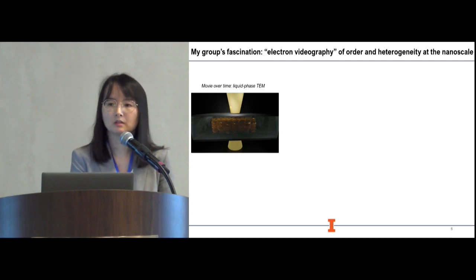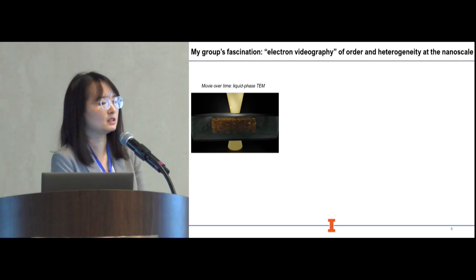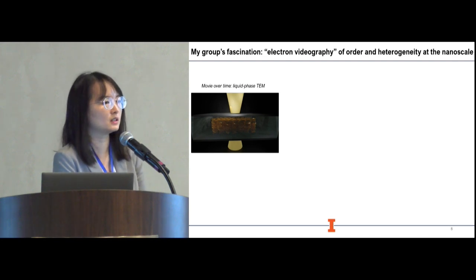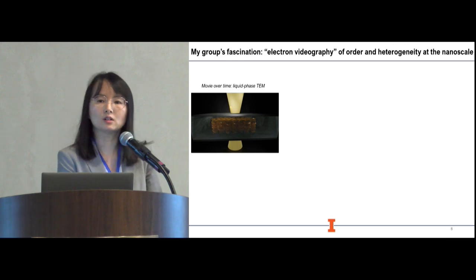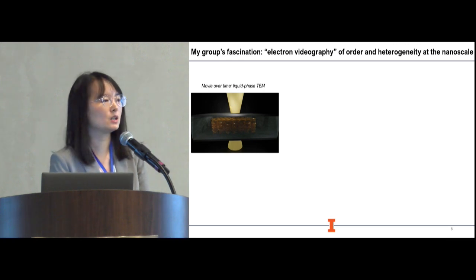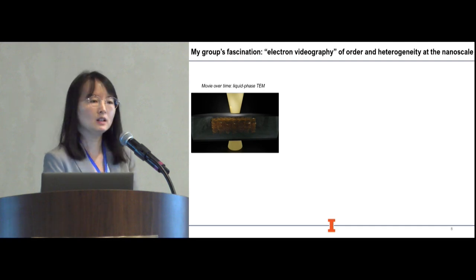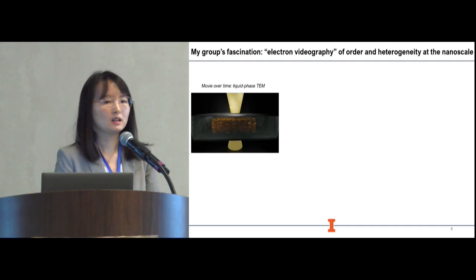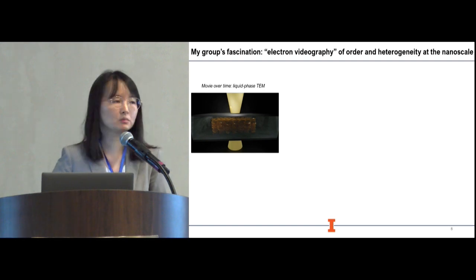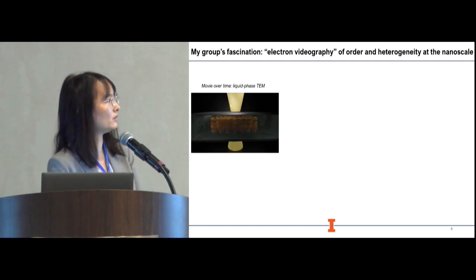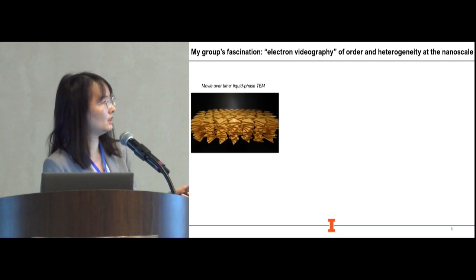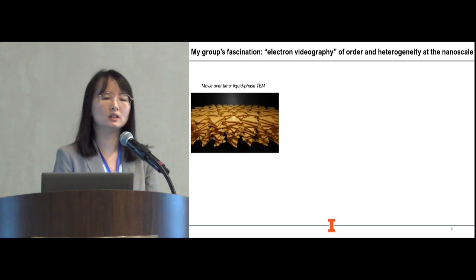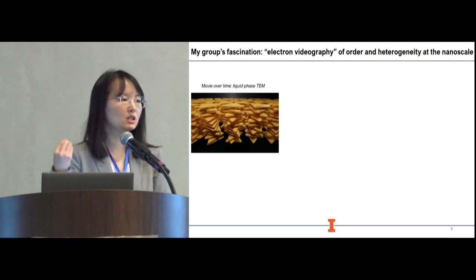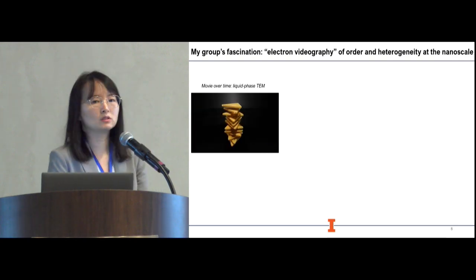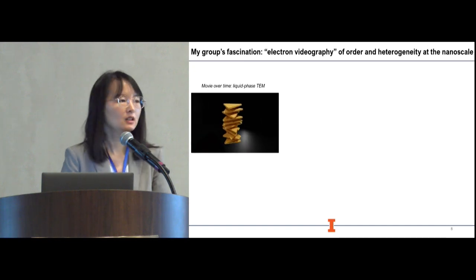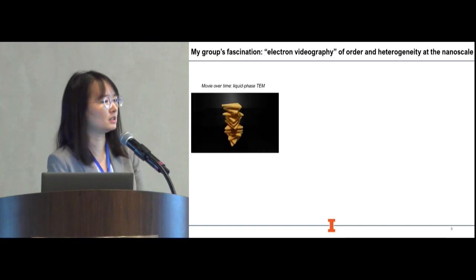In particular, my lab has been developing and utilizing this suite of tools which we refer to as electron videography. Electron videography goes beyond just taking one single snapshot of a sample. Instead, we can take movies. And in my group, we have 3 different ways to take movies. The first is liquid phase TEM, as shown in this animation, where you can sandwich and seal a colloidal particle suspension in the liquid phase TEM chamber. By doing so, not only can you resolve the nanostructure, you can also see the vivid dynamics in the presence of solution.